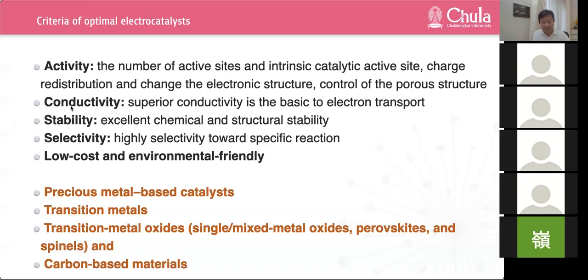And the next thing is conductivity. Of course, superior conductivity is the basis of electron transport in rechargeable zinc air battery electrochemical reactions. And what else? We need stability. Of course, zinc air battery ideal electrocatalysts must have excellent chemical and structural stability in the harsh acid and alkaline environment because of the increase in particle size, the accumulation of particles and the charge, and the change of the oxidation state on the surface of the electrocatalyst during the long-term charge-discharge cycle of the battery. So the electrocatalyst will gradually age and become inactive, which leads to the loss of battery performance.